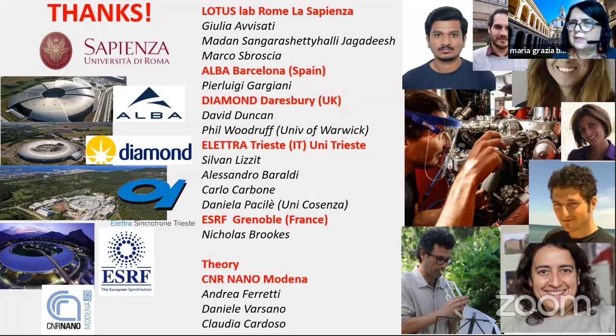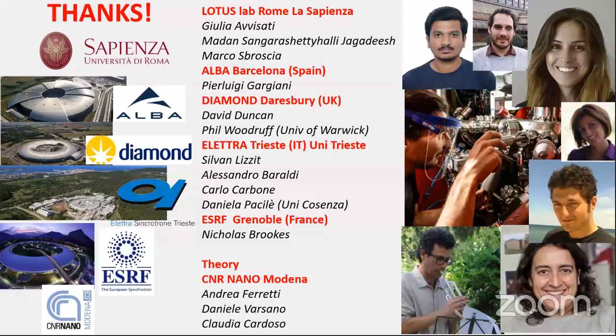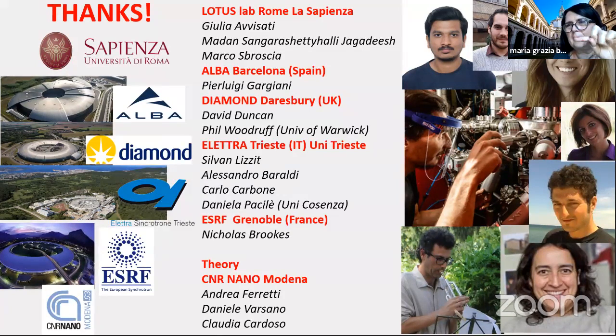Okay, so this is another important question. We were monitoring the adsorption of the molecules, and it's clear that at the beginning the molecules go in the valleys of the moire. You have valleys and hills. So at the beginning they go in the valleys. When they are in the valleys, there is a very good coupling with the ferromagnetic substrate. Then if you increase the number of molecules, you will see that there are no differences, so the coupling is lower.